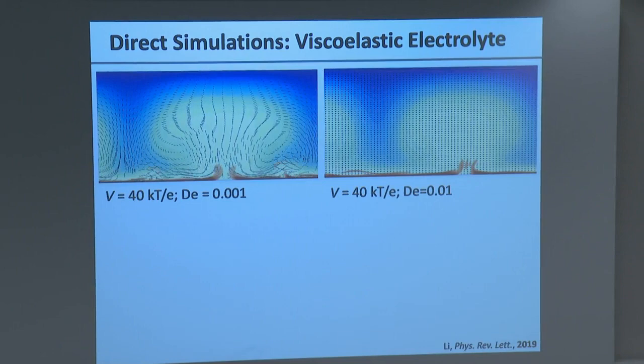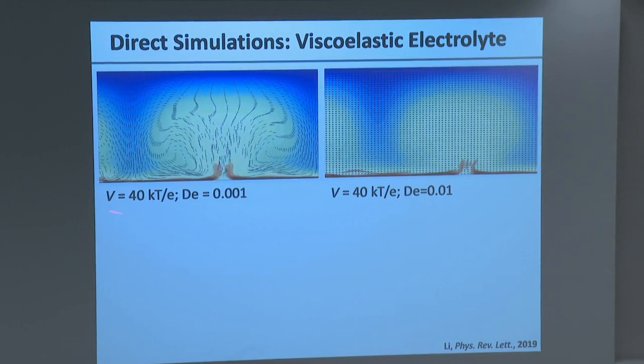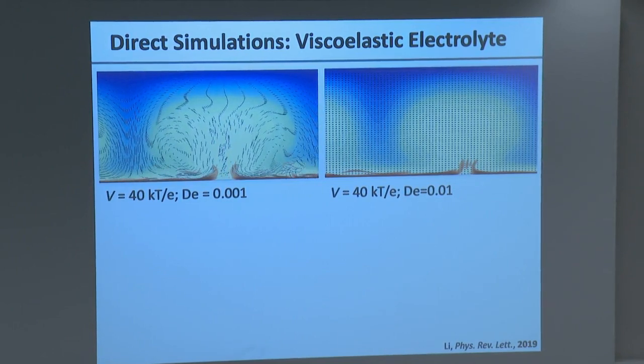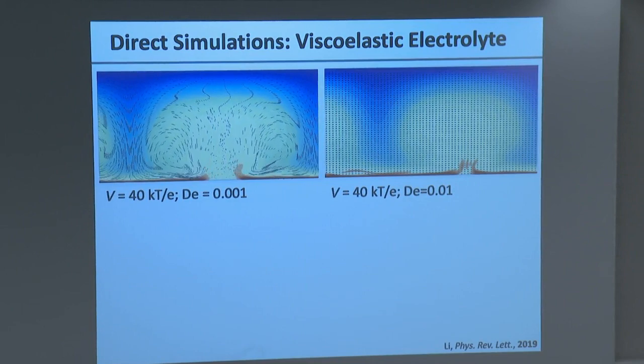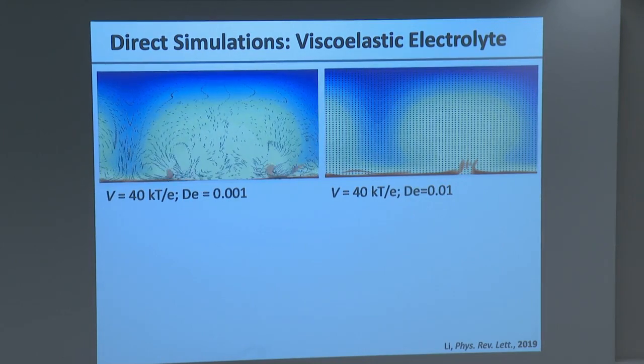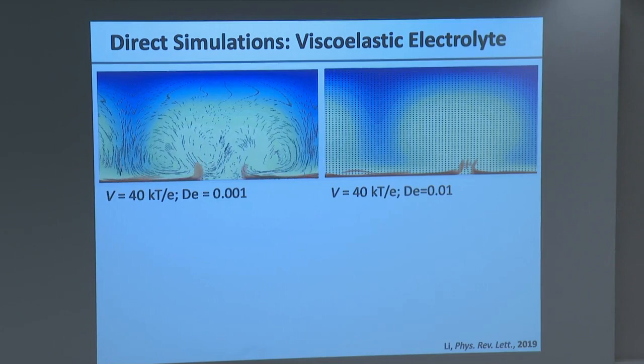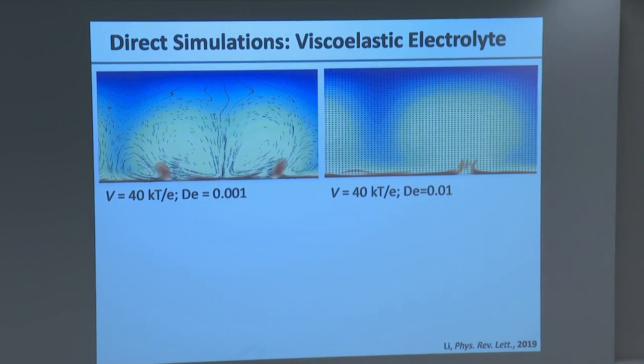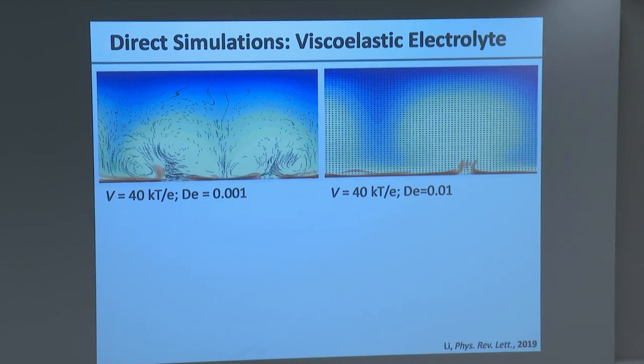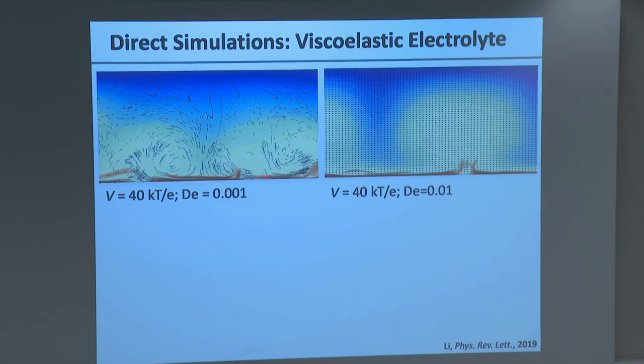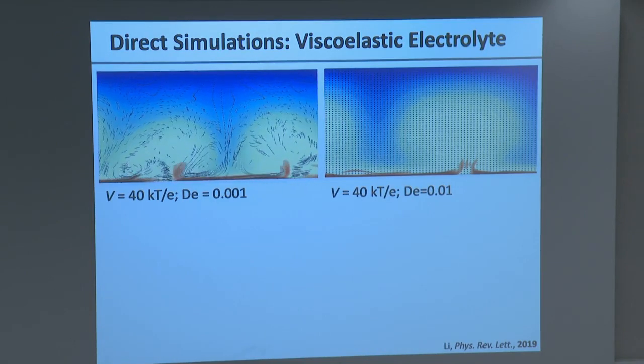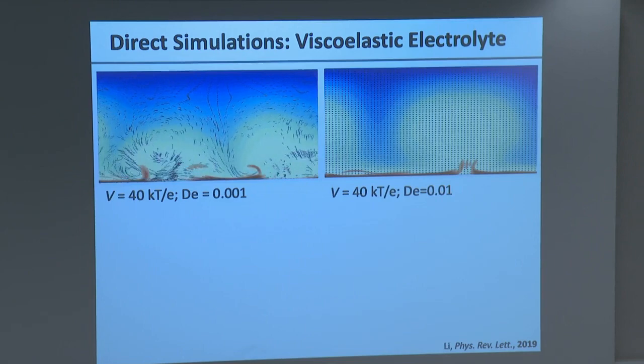So the left is essentially a video showing you what occurs. This number, the Deborah number, is actually a surrogate for the polymer effect. So a big Deborah number means a big polymer effect. It's kind of like a large polymer concentration. And if you stare at this, you will notice that as the fluid lines come down, this thing becomes red, so the polymers are highly stretched, just like I predicted earlier.